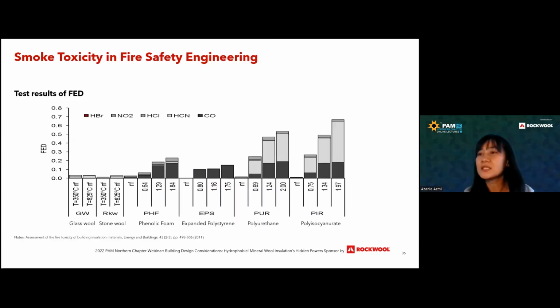So you see here is a graph. It's actually from a study; there's a link to that study below. I put it in the notes. What this graph shows is a comparison of the FED, fractional effective doses, of various insulation materials, which are Glasswool, Stonewool, as well as foam insulation. So remember, FED is asphyxiant gases, which cause hypoxia. The gases they measure here are hydrogen bromide, nitrogen oxide, hydrogen chloride, hydrogen cyanide, and carbon monoxide. So here is the thing: the higher the FED, the more toxic the material is.